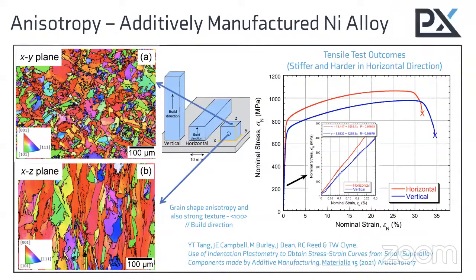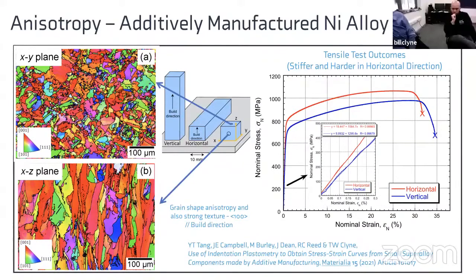Actually, we have seen some papers in the Journal of Additive Manufacturing on SS316, basically the steel, and there they have shown that because of the shorter slip path, this anisotropy comes in the bulk samples, like we are seeing here also. And I suspect that it may be because of grain shape also, like in the Ti64 and SS316 people have reported. Yeah, you're absolutely right. And unless you do some very detailed modeling, it's quite difficult to separate the two.